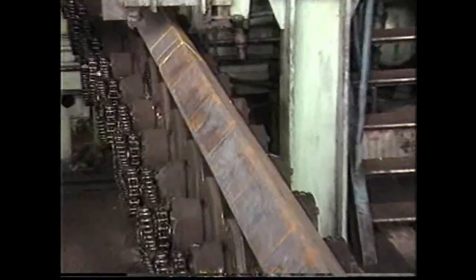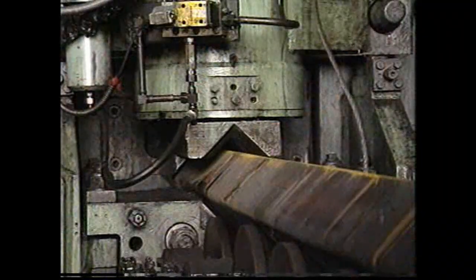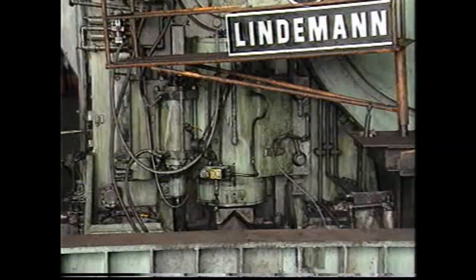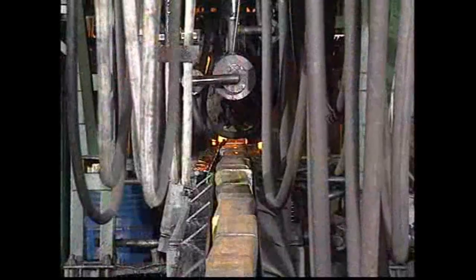Steel billets of pre-calculated length of 500-900mm are cold sheared using a cold shear of 1,600 tons capacity. The cold shear can make 4 cuts a minute.